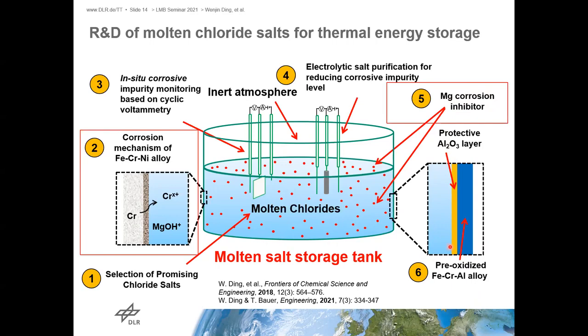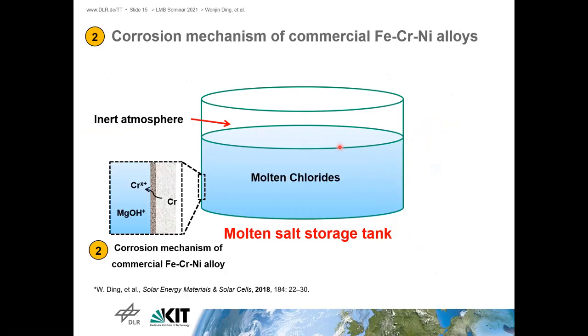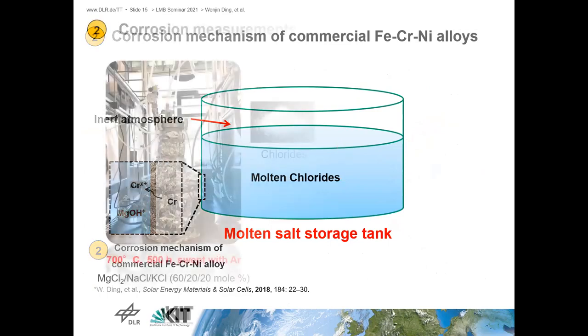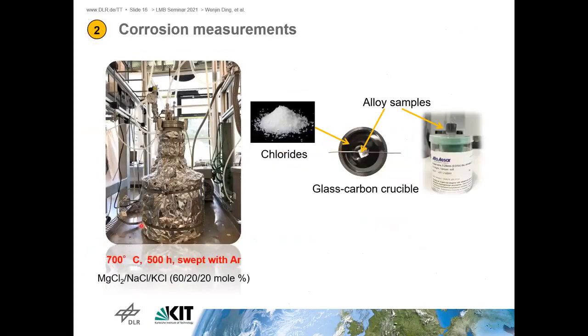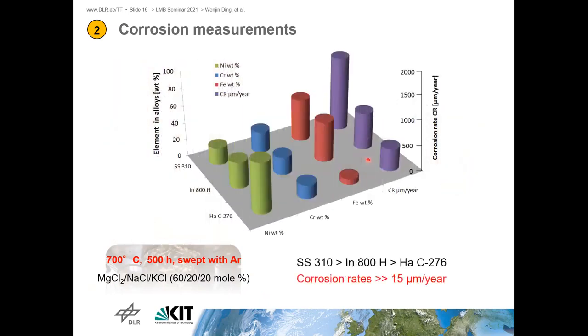But due to the time, here I just introduce these two topics because they may have some knowledge for liquid metal battery development, and it can help to control the liquid metal batteries' corrosivity. First is the corrosion mechanism of the conventional iron, chromium, and nickel alloy. We do the immersion test at 700 degrees C for 500 hours, and the atmosphere is argon. This is the atmosphere as in the liquid metal battery, and also for the thermal energy storage application. We use these salt mixtures and put the alloy samples inside and heat it up to high temperature, and after 500 hours take it out to do the analysis.